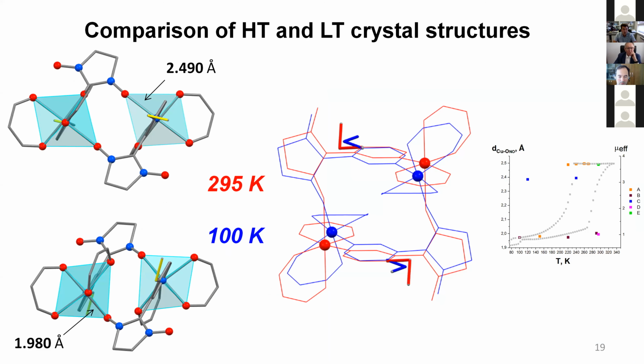It was found that the transformation of structure below the phase transition point leads to a change of the elongated axis of oxygen in the copper binuclear fragment, a change in position of the ethyl group, a change in the isoquinoline molecules, and the copper distances decrease by more than 1 angstrom, and the intermolecular distances between oxygen atoms of nitroxides elongate by 0.5 angstrom.